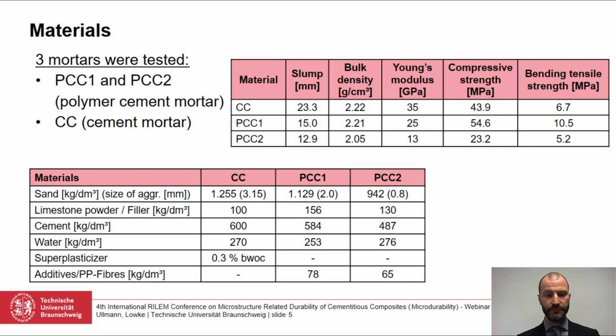The recipes. We have some main differences we can identify between the recipes, and that is in the maximum size of the aggregates. The CC mortar has a maximum size of 3.15 mm. The PCC mortars are finer in their aggregates. They have 2 mm and 0.8 mm. All 3 materials used ordinary Portland cement, and what is worth noting is that the PCC mortars contain PP fibers. A look at the hardened properties,